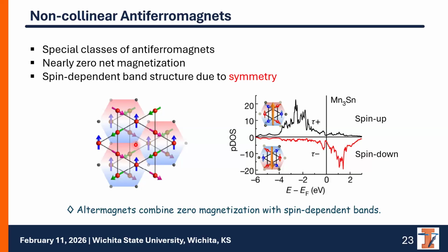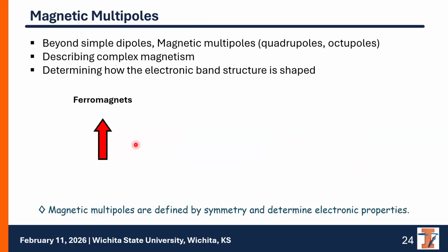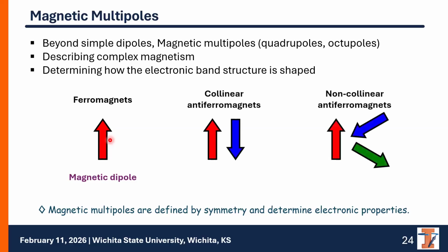At this point, we need to change our language. In the case of ferromagnets, the magnetism can be described by a magnetic dipole because they have two poles, North Pole, South Pole. However, for the more complicated magnetic materials, we need to use higher order magnetic multipoles, such as magnetic quadrupole or magnetic octupole, septupole, those kinds of things. So the magnetic multipole order is determined by symmetry. But the important thing is the magnetic multipole is not just a mathematical construct. It actually determines the electronic band structure and the electronic property of magnets. Okay, now we can define the spin state of complicated non-collinear antiferromagnets.